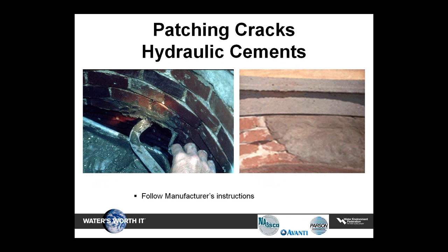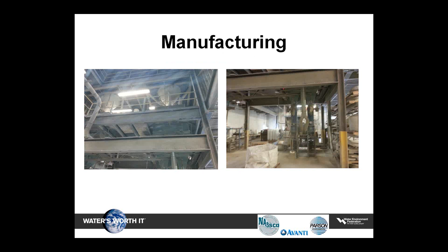Cementitious patching materials can be used to fill in gaps, voids, or holes that may be excessively deep prior to installation of the cementitious lining. Most of the manufacturers offer this type of product that is compatible with their lining material. This is an important point to consider when placing more than one surface bonding product in the same manhole. Set times for patching materials are usually in the 30-minute range.